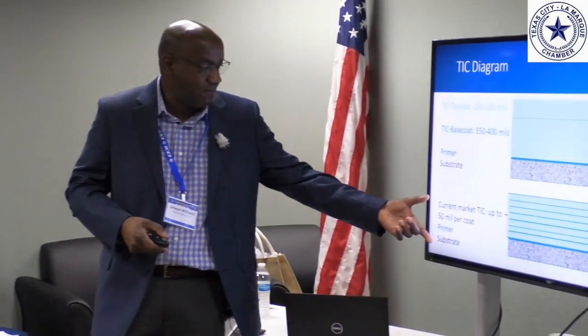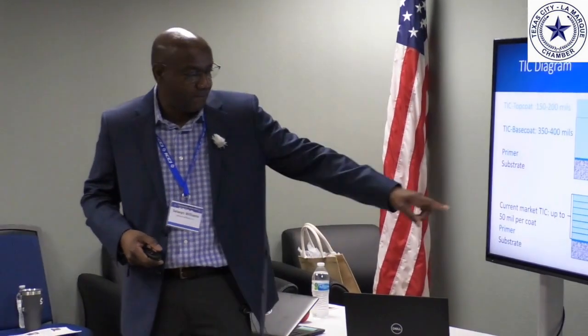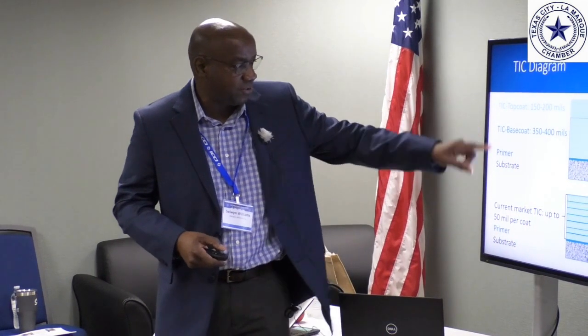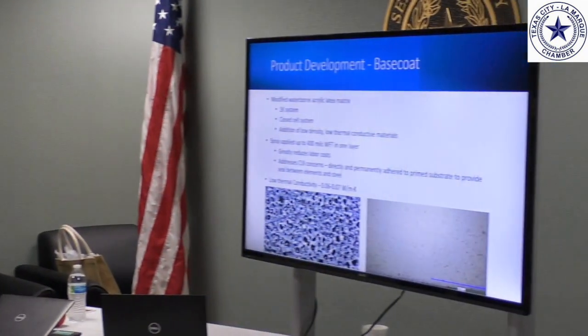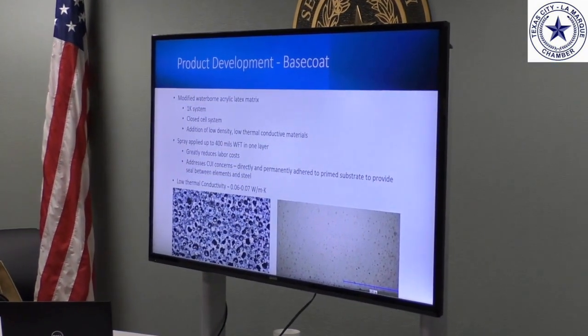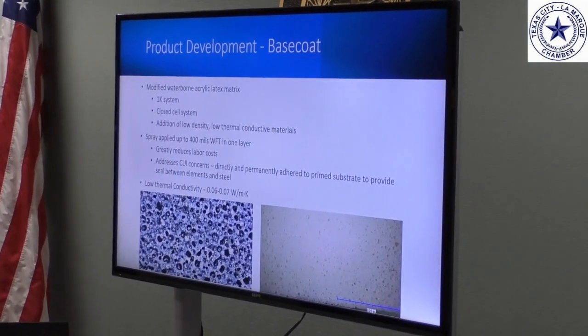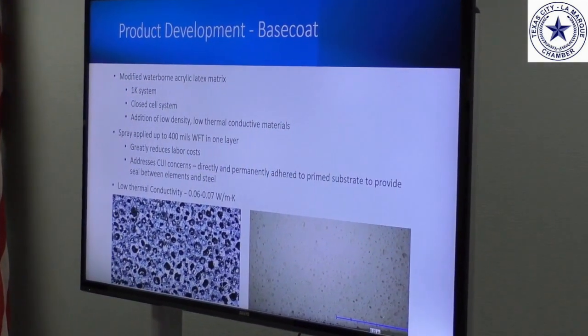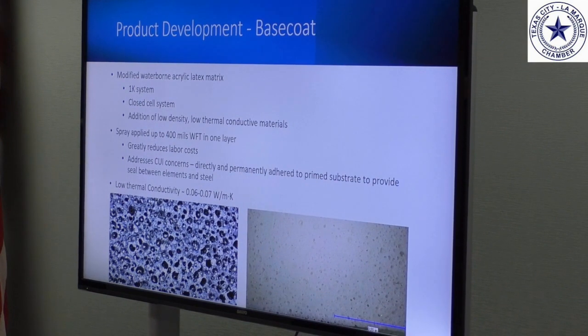The bottom shows the current TIC in the marketplace. As I mentioned earlier, 50 mils per coat. To get to this thickness, you have to apply 8 coats of paint at 18 hours between coats. So in the product development where we are now, we have a one-component system. It's a closed cell, low density material. We can apply up to 400 mils, and it addresses the CUI concern.